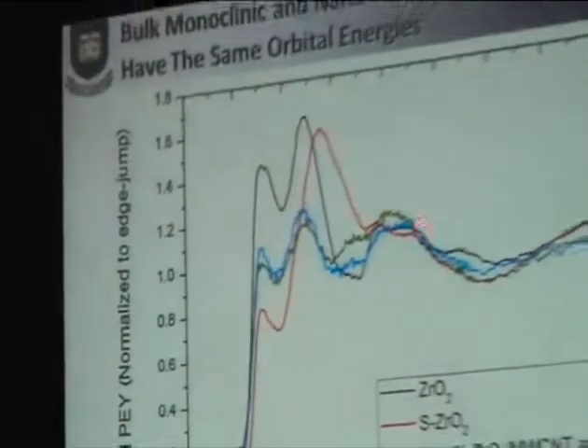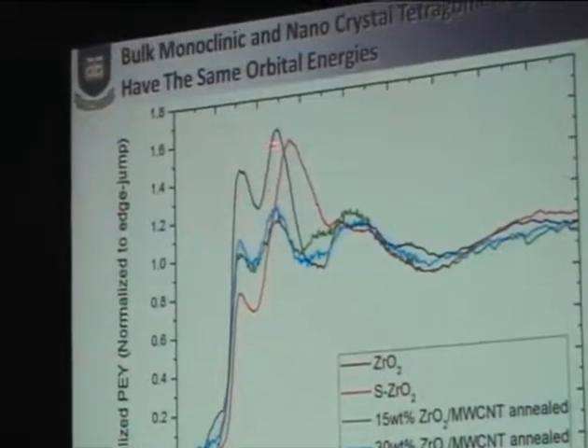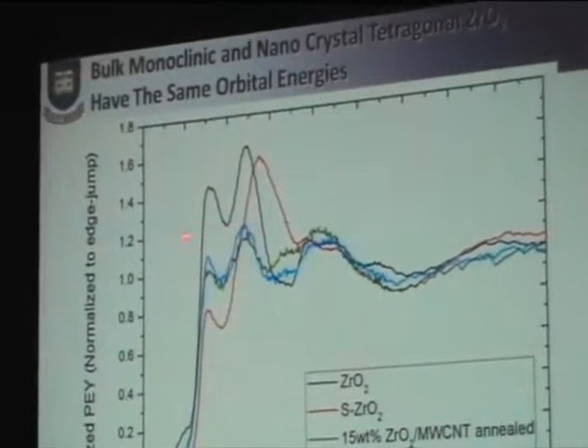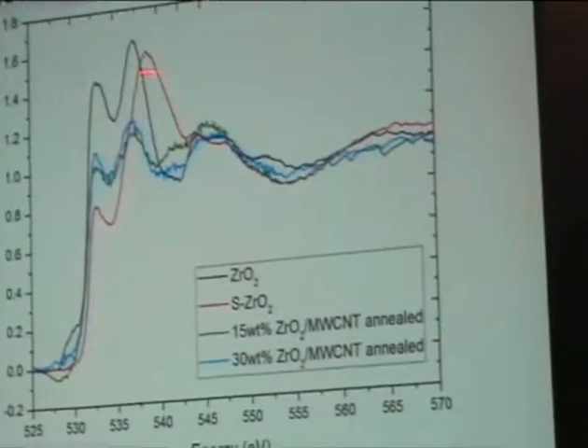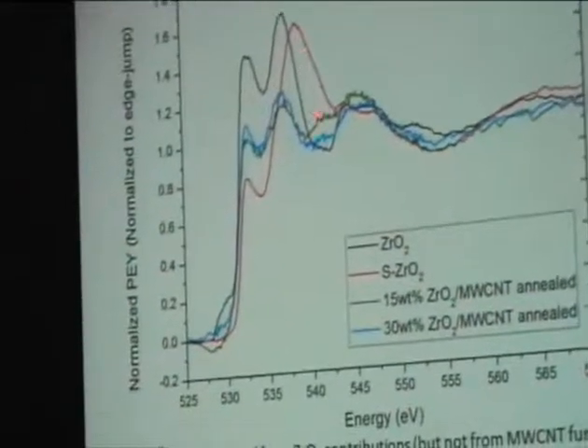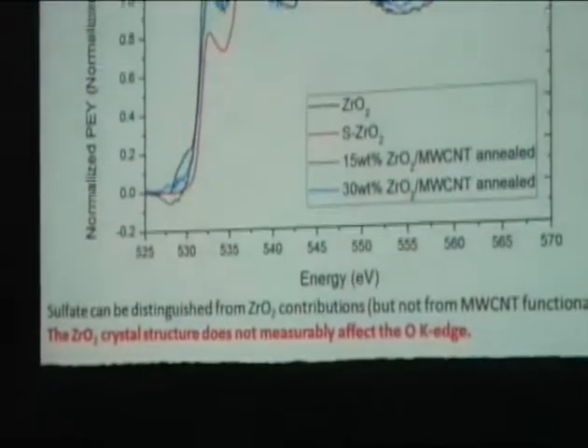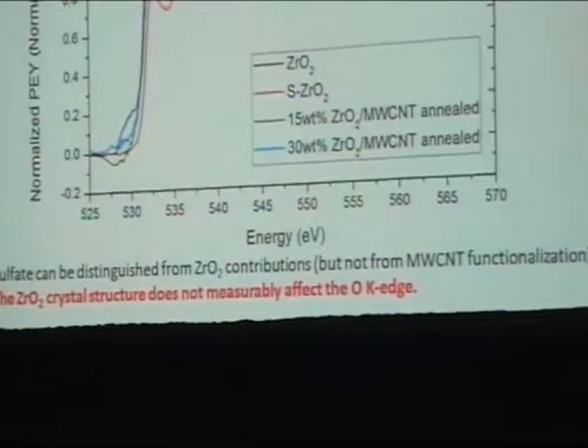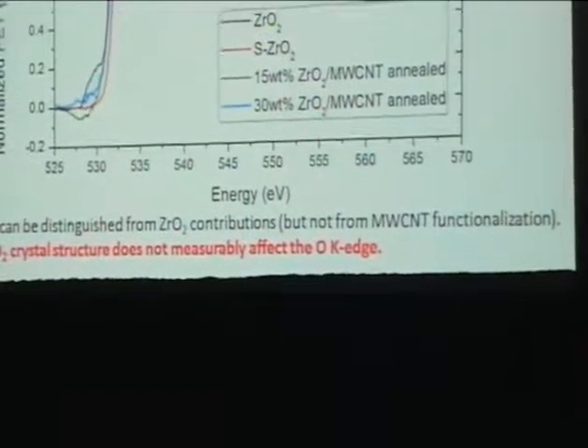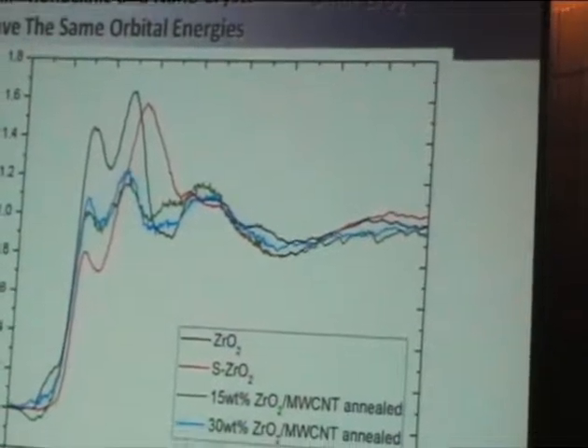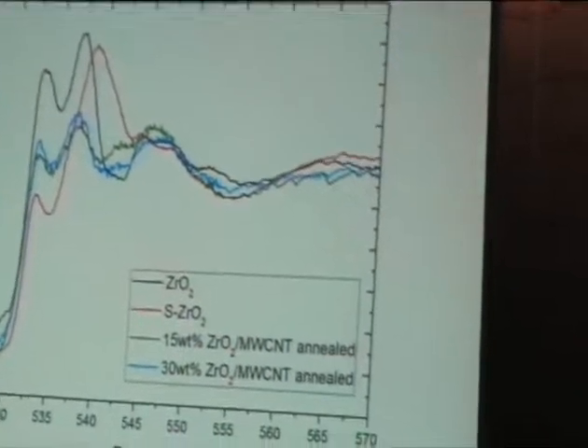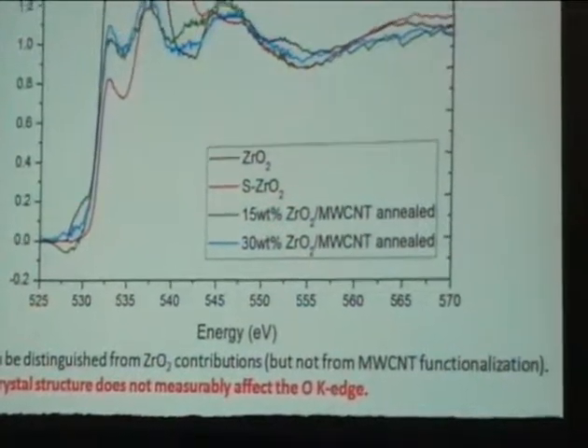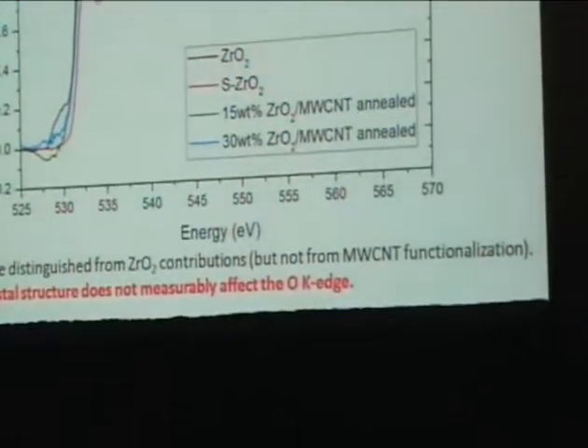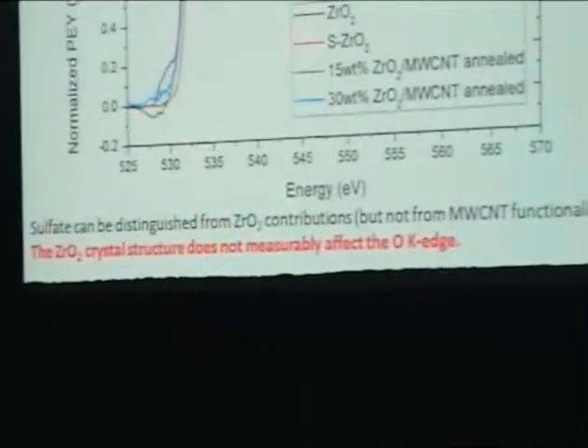and the blue here, and we have a bulk zirconia there. You can clearly see that while the sulfated bulk has a high intensity here due to the sulfur, the zirconia, now tetragonal, has the same peaks as the bulk. So there's no electronic perturbation when we go from monoclinic to tetragonal. It is all due to the electron sharing in the orbitals, to the extent that the intensity changes.